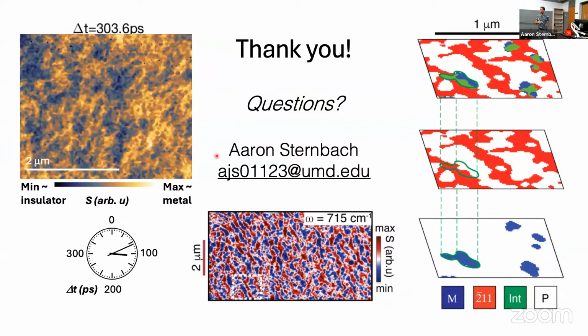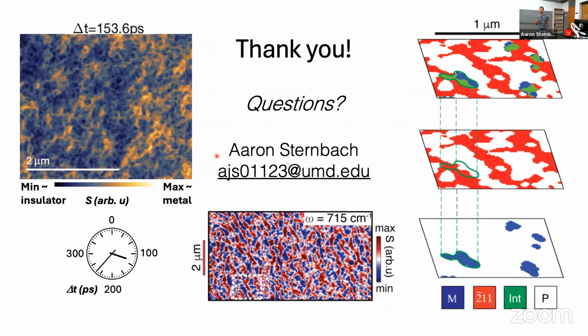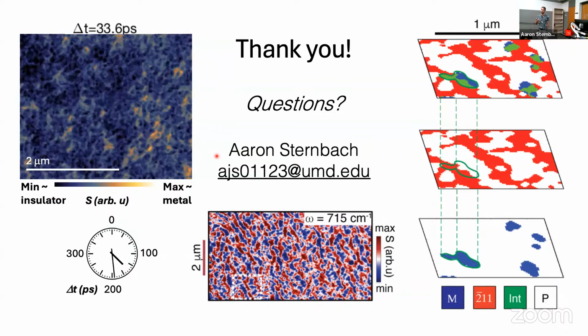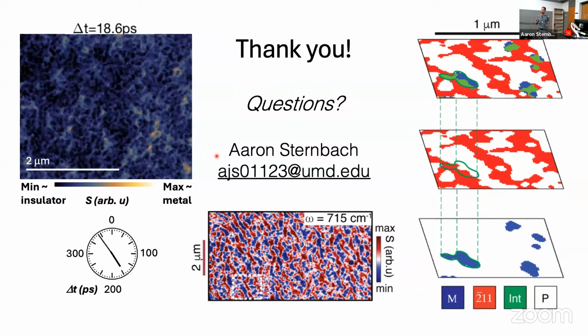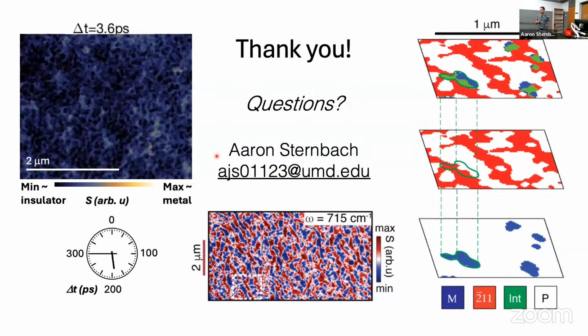But from X-ray measurements, the crystallinity is actually pretty good. So misorientation between the grains is only a few percent. Yeah. Sputtering gives you grains that are about 10 nanometers. So maybe.